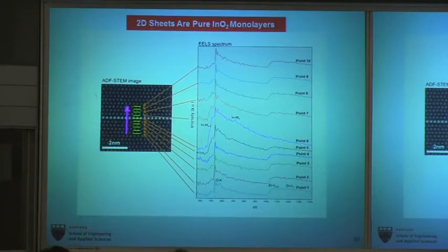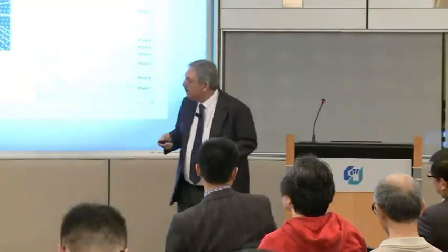In fact, with today's aberration-corrected microscopes, you can then do EELS analysis. So you can do an EELS analysis of 3 atoms there, or a column of 3 atoms there. You see it has the characteristic indium peaks. And if you move off, you then see the characteristic zinc oxide peaks, which are here. So we know the indium is localized to a monolayer, or periodic arrangement of monolayers.